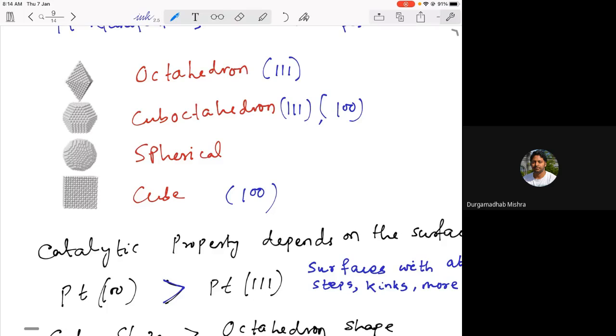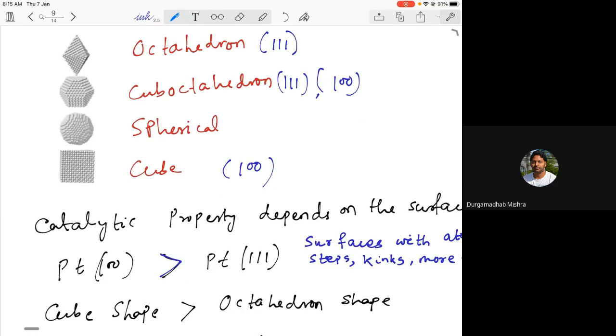And mostly the surfaces that are best for catalysis are the ones which have more defects or steps or kinks in their surfaces. So if the number of defects is more, then those surfaces are better for catalysis. They have more dangling bonds, so they are good for adsorbing the fuel and dissociating it. In the case of platinum, it was observed that the platinum 100 surface is much better compared to the platinum 111 surface, and therefore people started using it.